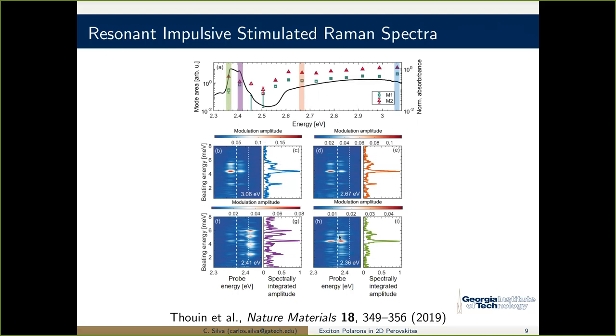And in that case, we still see the Raman activity centered around the maximum of the bleach or the absorption spectrum of exciton A. But now this mode, this is what we had called M2, is completely dominant over all of these others in amplitude. And in the resonance Raman experiment, the amplitude of the Raman mode tells you the degree to which that particular normal mode is coupled to the photoexcitation. You've injected a photoexcitation, through electron-phonon coupling you've set the crystal in this sort of coherent vibrational motion, and it is mainly this one that is coupled to exciton A, with much lower, let's say, Huang-Rhys parameter for all the other modes. This one, for example, is completely gone, well within, of course, the signal to noise.